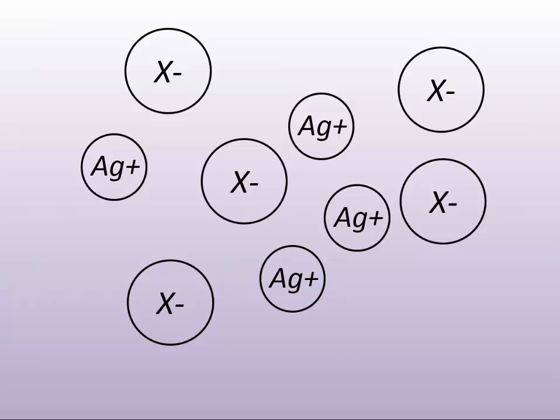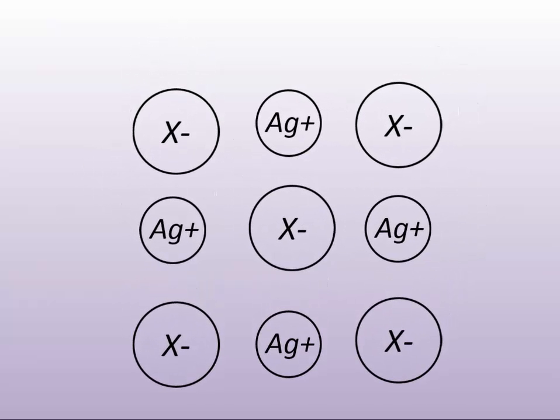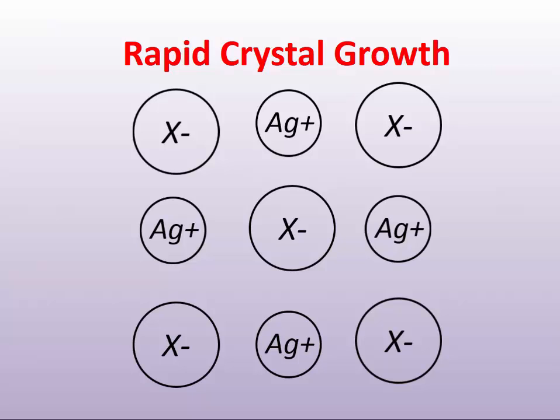Through the photographic chemist's studies, there is what's called a nucleating event — in crystal growth, it's called a seeding event. All that needs to happen is about six ion pairs congregate and associate to start the crystal-forming process. Then they coalesce. Once that nucleation happens, you get really rapid crystal growth, and all of a sudden, crystals of various shapes and sizes are being formed because of differences in time, temperature, and stir rate.